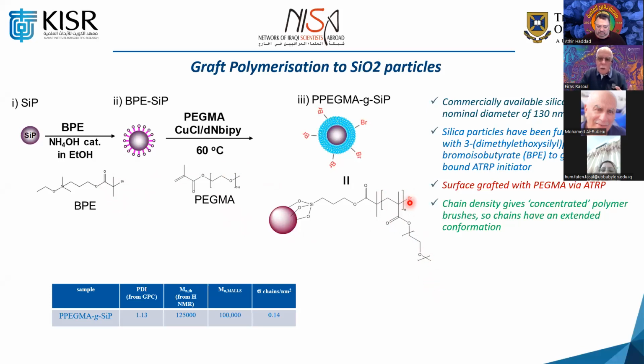We're still having this bromo functional group, which is useful, as you see it here. And of course, this material, the silica, is commercially available. We just got it. The size of it is about 130 nanometer. We reacted with this compound, and then we did a controlled ATRP initiator. We did controlled polymerization using polyethylene glycol methacrylate via ATRP initiation, and then the chain density, we measured it. We see the PDI, it is pretty narrow.